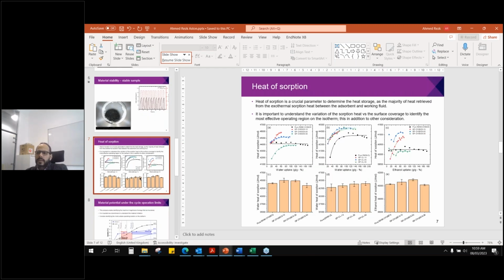The second characteristic, or the second property we measure, is the heat of sorption. So for this case study, I measure the heat of sorption of the composites against water and ethanol. And it is important to look at the heat of sorption against uptake. So the y-axis here is the heat of sorption, and the x-axis is the concentration of the water uptake. And we need to look at whether the heat of sorption is stable across the surface coverage or varies, which guides us on where most of the heat can be gained from the isotherm.